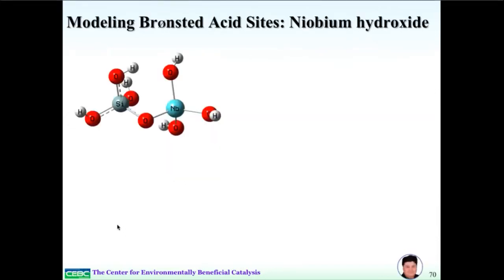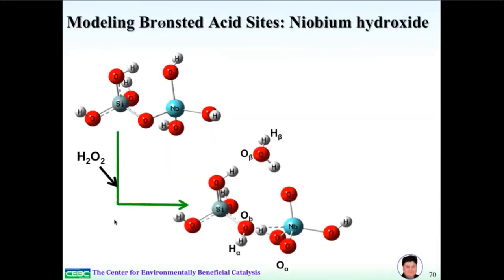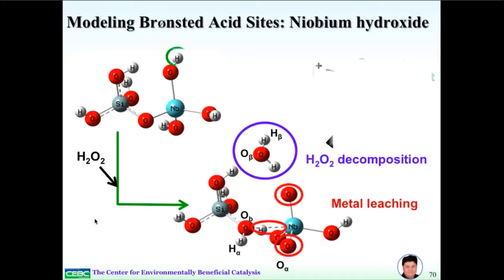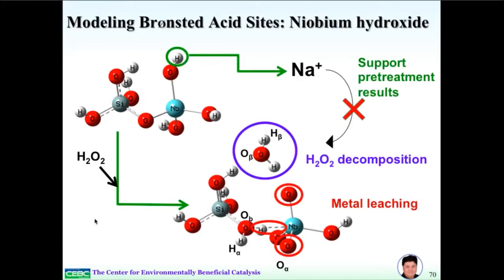We can also look at the Brønsted acid sites. So by looking at niobium hydroxide here, we can see what happens when we add hydrogen peroxide to this. One finds that it actually does end up with two problems. You get H2O2 decomposition from this acid site, and you also end up with the breaking of this Nb-O bond to get metal leaching into the liquid phase. If you pre-treat this, essentially replacing this hydrogen with sodium, you actually inhibit this particular pathway for the decomposition.